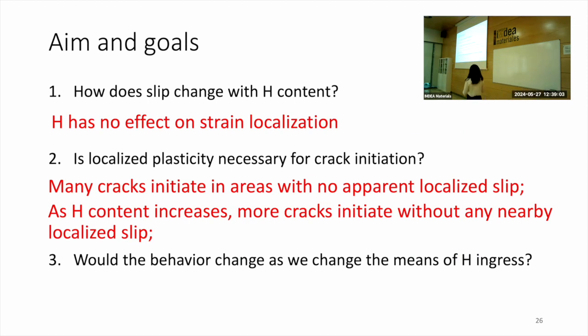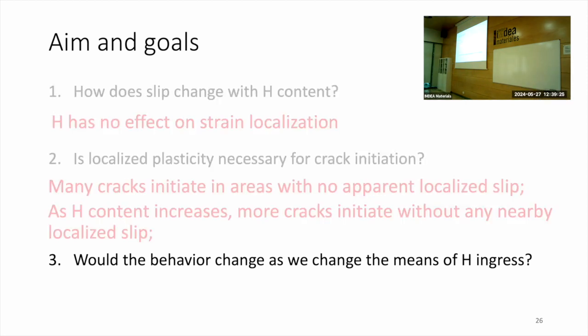Is localized plasticity necessary for crack initiation? We observed many cracks initiate in areas with no apparent localized slip. As the hydrogen content increases, we see more and more cracks initiate without any nearby slip. Let's move on to the third question. Would the behavior change as we change the means of hydrogen ingress?